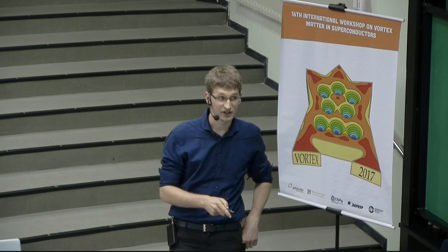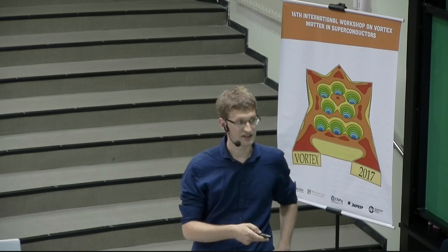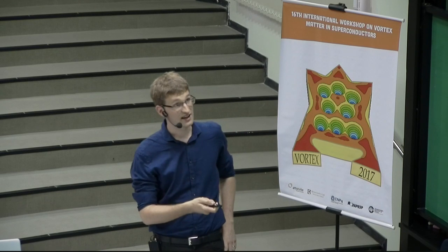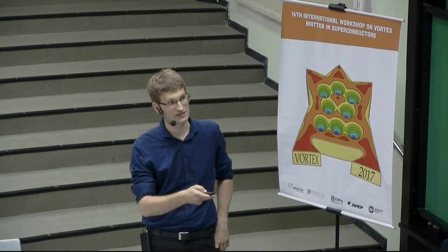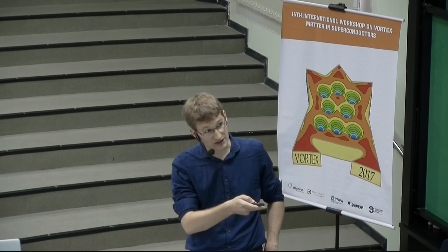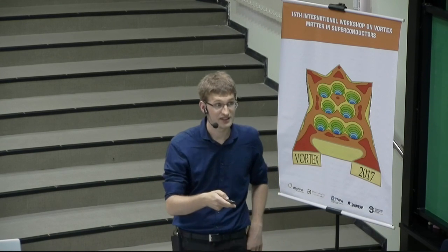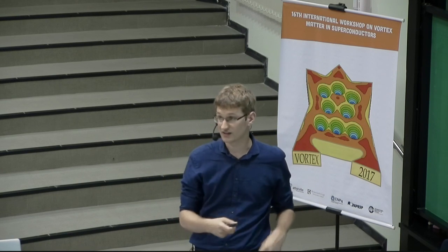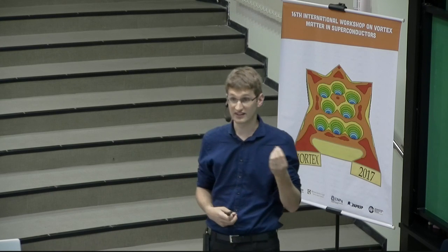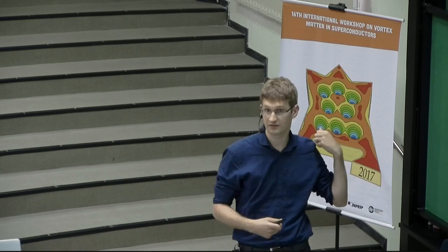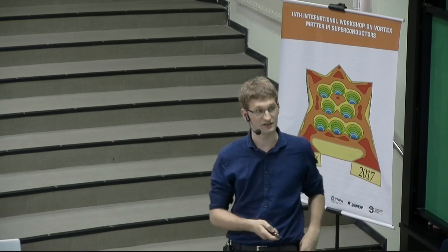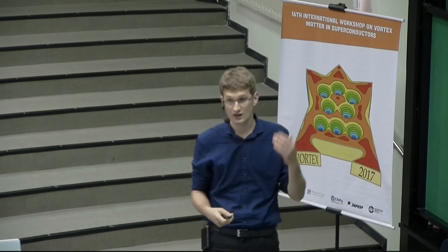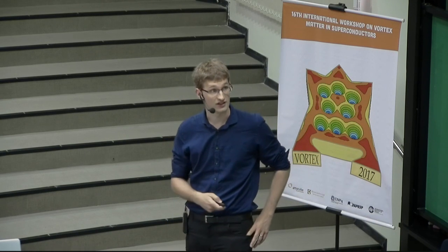And I think we can very well account for this deviation by taking into account defect doublets, which correct the critical current. And at high fields, we have a linear dependence in the magnetic field, in the density, and the decay of the critical current, which is faster than 1/B, can be understood by the fact that the pinning force is not a field-independent quantity, but acquires a field dependence, because vortices which are in the back, they would like to enter the defect. And for large inclusions, we even see a non-monotonic behavior of the critical current.